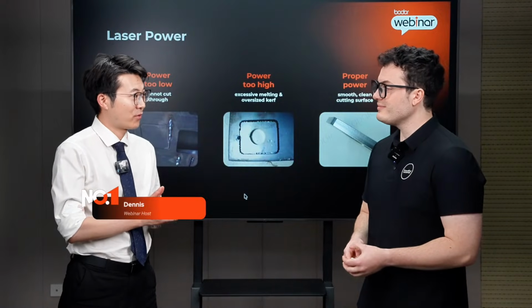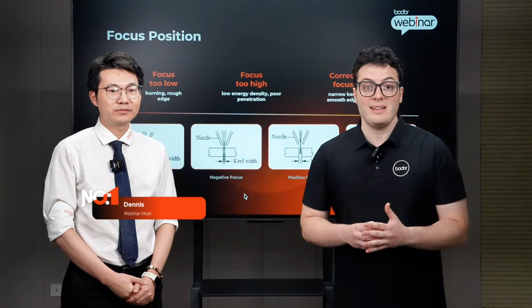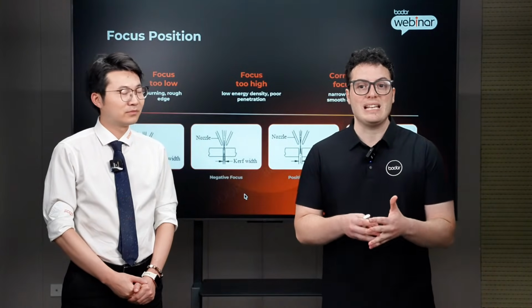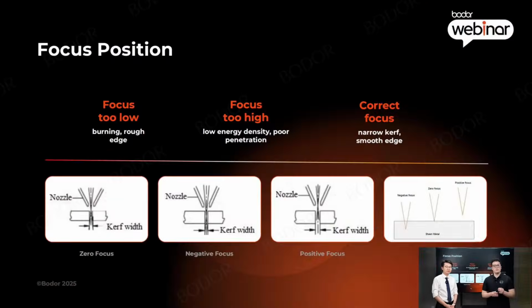And after power, I guess it's focus, right? Yes, the focus decides where that energy is concentrated inside the material. If the focus is too high, the energy spreads before it reaches the core of the sheet, and the piercing becomes poor. If the focus is too low, you push the energy too deep, and you can burn or roughen the edge.